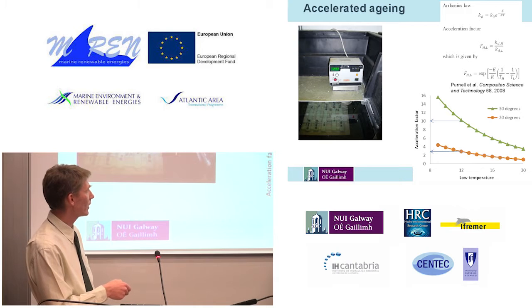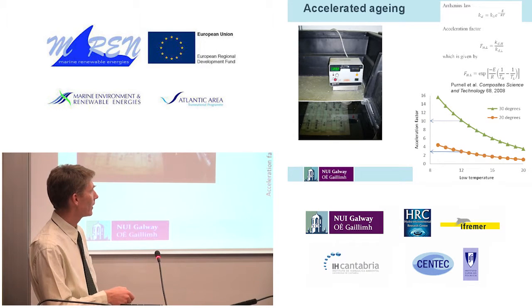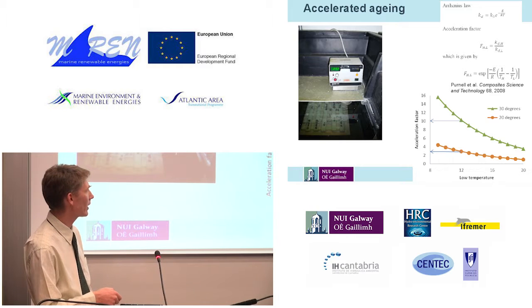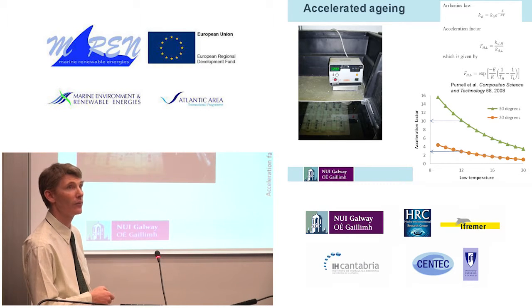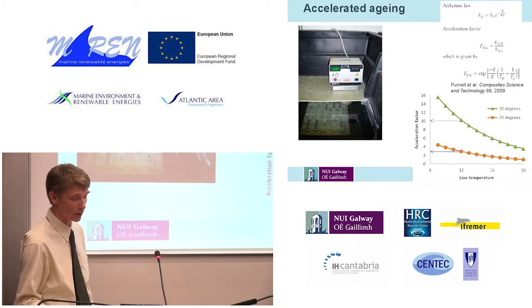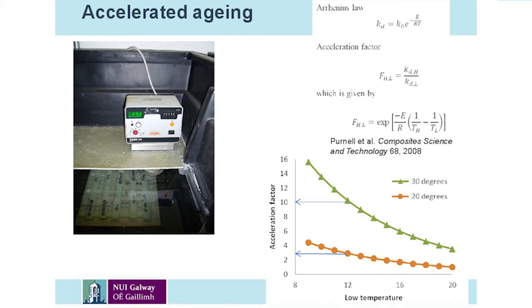I also had some samples in room temperature water, and you can see that that actually has an acceleration factor of maybe as much as 3, which you might not expect. One thing I would say is that it is important, in your water bath, to have it stirred and maintained at a constant temperature, because the temperature differences here are not very big, and so if you get a gradient in your water tank, that's going to have an effect on your results.